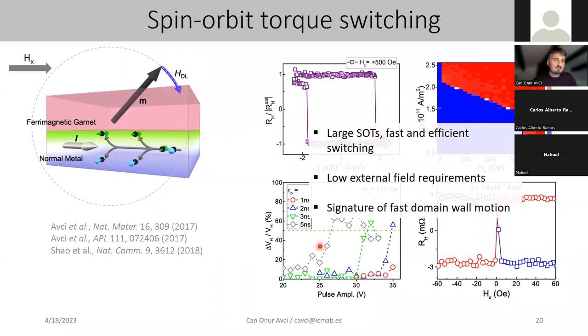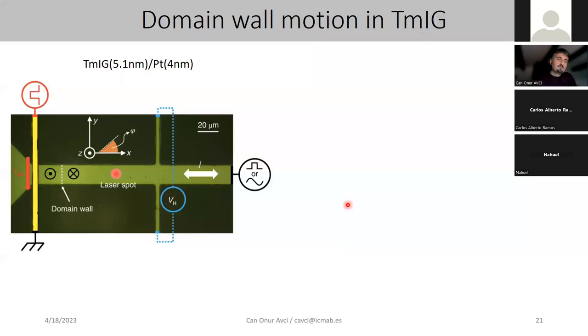And to test this hypothesis, we went to the next study where we patterned some devices here. Now we are using the same bilayer film, platinum thulium iron garnet. And this time this green area is basically our domain wall track, which is this material. The dark area is basically the substrate. And you have this yellow part, which is basically the domain wall nucleation line. So what we wanted to do is basically nucleate a domain, create a domain wall, and study its current-driven dynamics. And to do that, we are using a focused laser MOKE system, basically, which can detect the magnetization locally at a given position in the device.